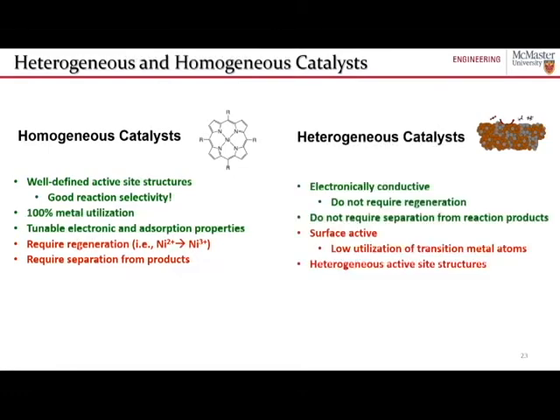One is that they're electronically conductive, so they've got an infinite source of electrons available, and therefore they don't require regeneration. They don't need to be reoxidized or re-reduced in the way that homogeneous catalysts are. Because they're in a different phase from the reacting species, they don't require separations downstream as well.